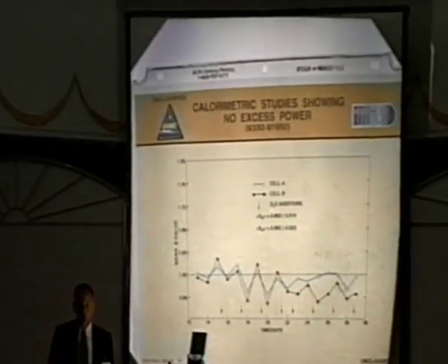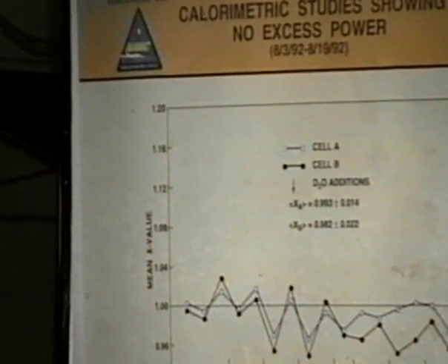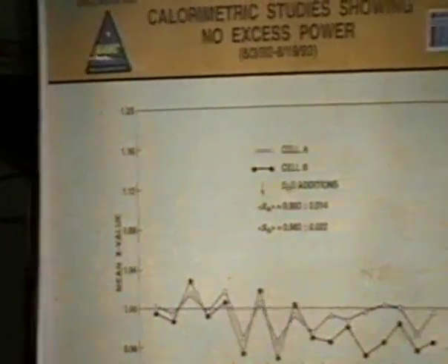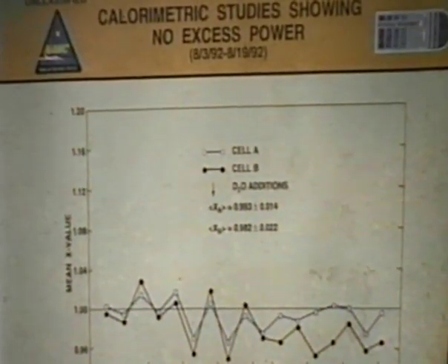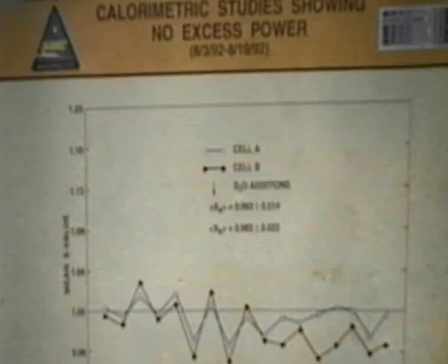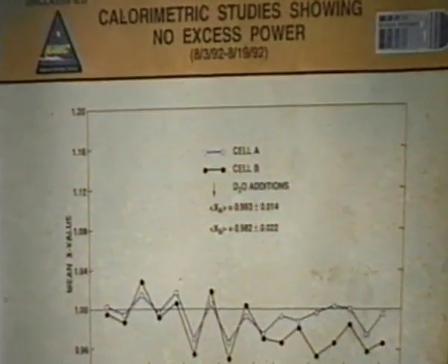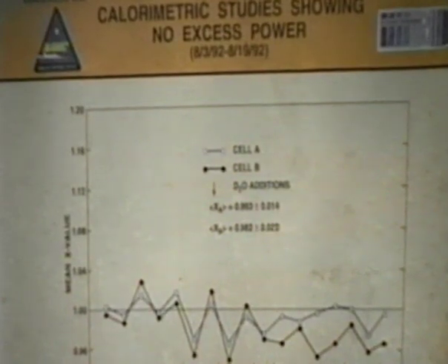But like most people, most of our experiments do not produce excess heat. I would say only about 1 experiment in 4 gives us excess heat. This is what it looks like in many experiments that we run. The heat out to heat in ratio, if anything, we're a little bit below break even. This is break even right along here, and this is the net average. It's slightly below 1, and most of our experiments look like this. So our success rate is about 1 out of 4 experiments that produce excess heat.